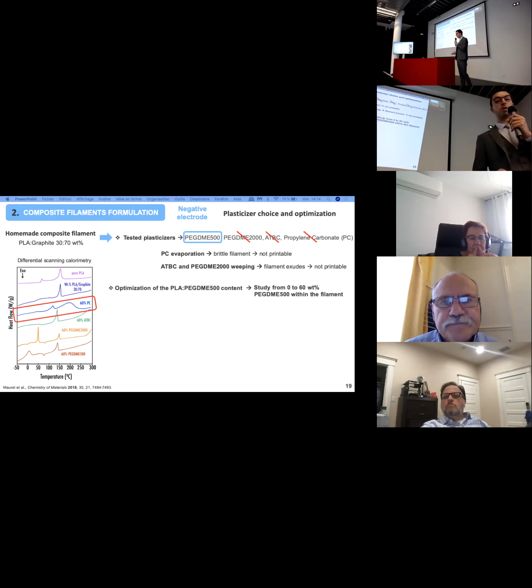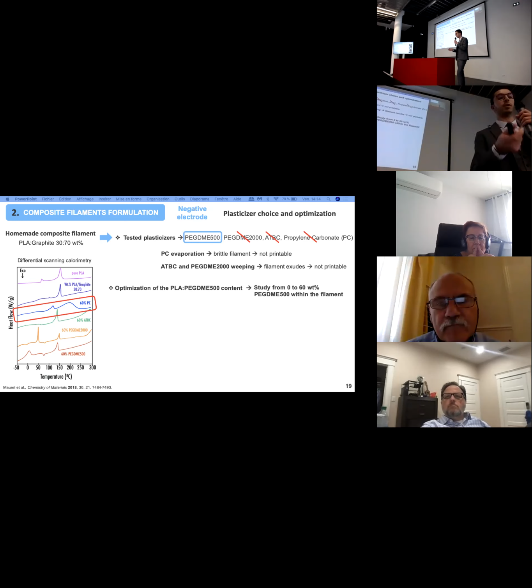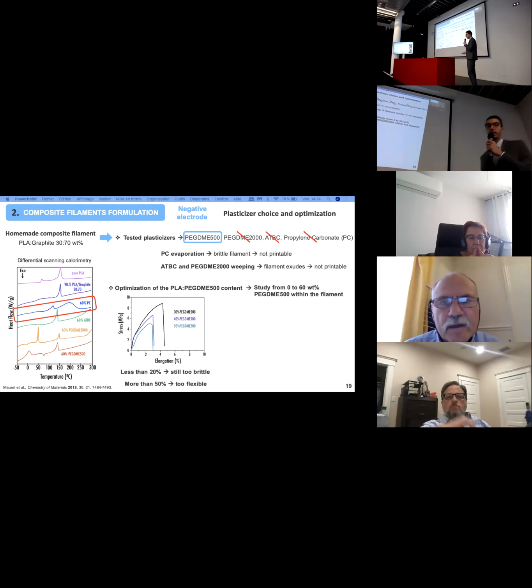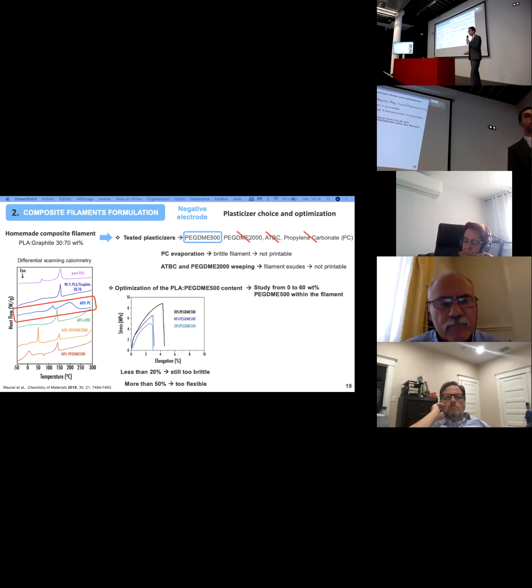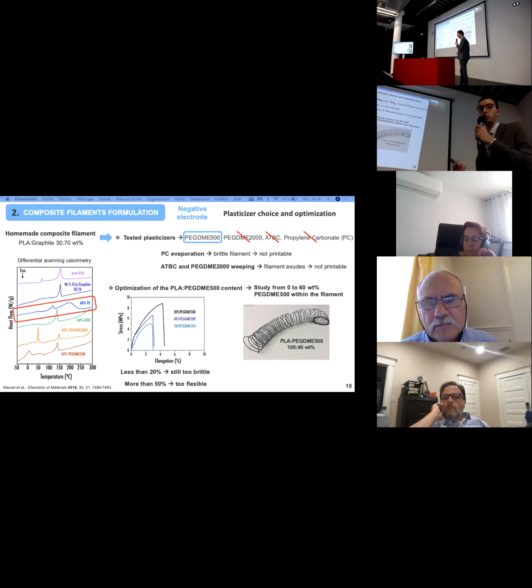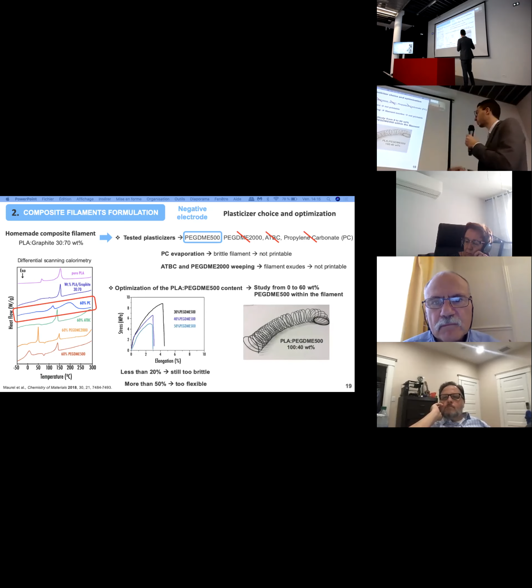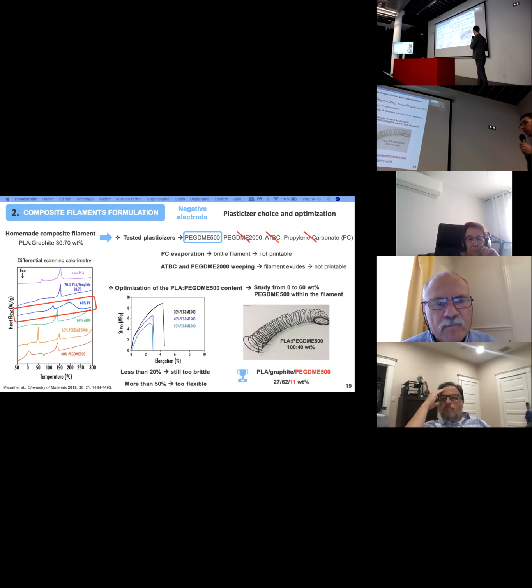So we pursued our optimization and we tried to optimize this plasticizer content. We made different compositions, and did a printability test as well as a tensile strength test in order to determine the Young modulus. Here we saw, thanks to the printability test, that if you have a filament with less than 20% of your plasticizer, we got a filament that was really brittle. While if you have a filament with more than 50% of plasticizer, the filament was too flexible to be printed. And so finally, thanks to the printability test we have done, we concluded that the filament containing 40% of PEG-DME 500 was the optimized one. And it corresponds to this ratio here, so 27% of PLA, 62% of graphite, and 11% of this type of plasticizer.